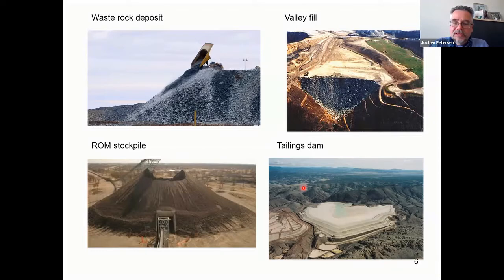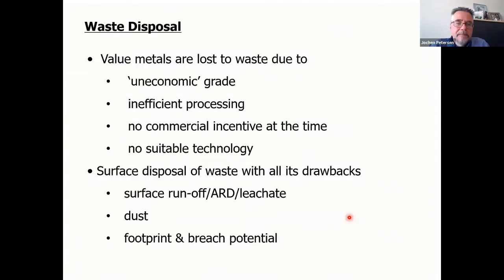So this is just a nice aerial picture of the disposal, where you basically take the fine material that comes out of concentration processes and leach residues, and as a slurry, you let the slurry settle out, and the water is then decanted either through sucking it away or just seeping through the deposit as a whole, and you just build up layers and layers and layers of this deposited material. But all the surface disposal is important. Very little of that material is backfilled, and most of the material is disposed in surface deposits with all their drawbacks. And I'm not going to go into much detail because they're all well known.